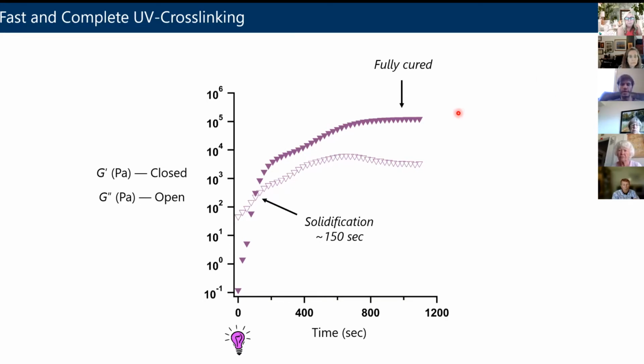So there's 2 data sets here that both come from the same experiment. There's something called the storage modulus, which is the elastic contribution to the stiffness. And there's something called the loss modulus, which is the viscous contribution. So you can think about this as being in between a liquid and a solid. If it were purely solid, it would just be elastic. If it were purely liquid, it would just be viscous. Polymers tend to be somewhere in between.